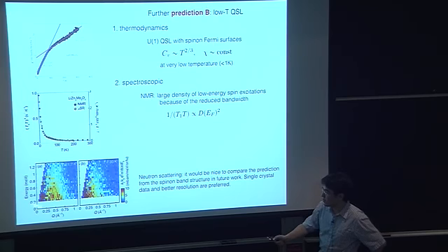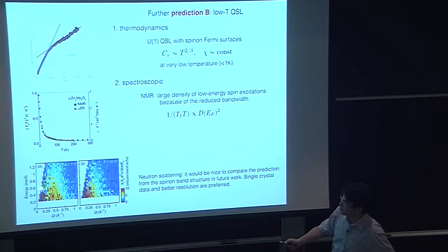And neutron scattering is not particularly conclusive because of very poor resolution. So the experimentalists claim a gapless spectrum, and it's consistent with the spinon Fermi surface picture. But it's very hard to obtain some structure from the current data.